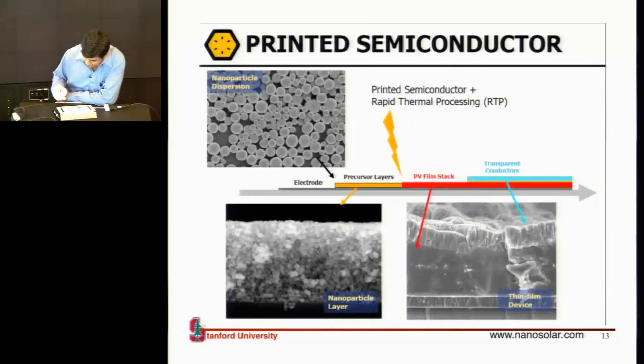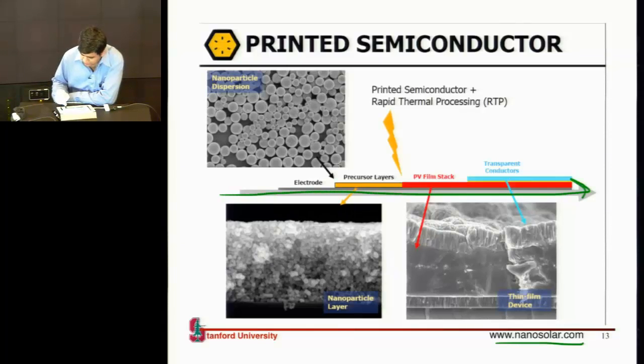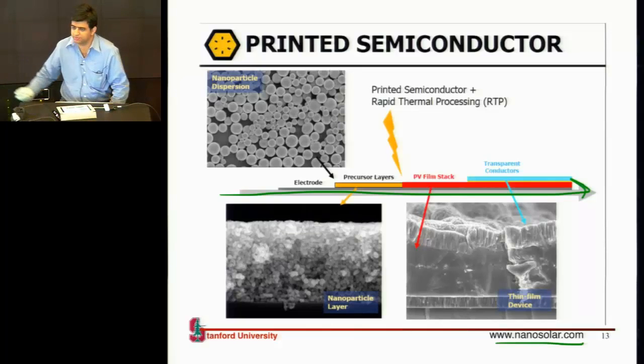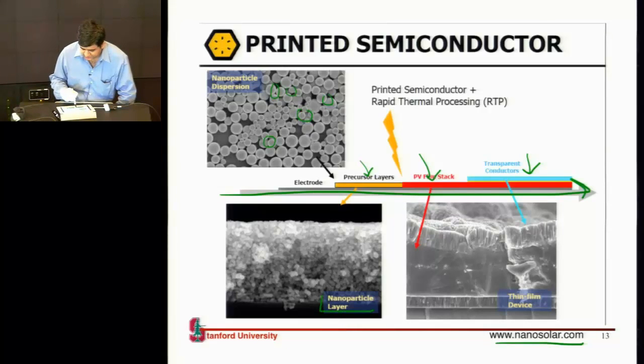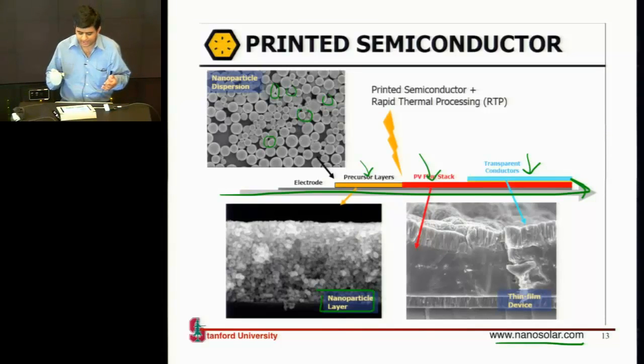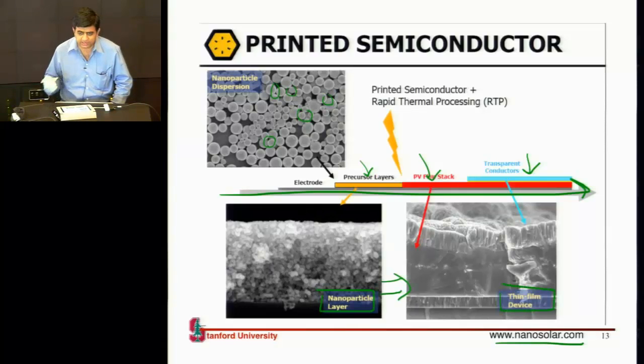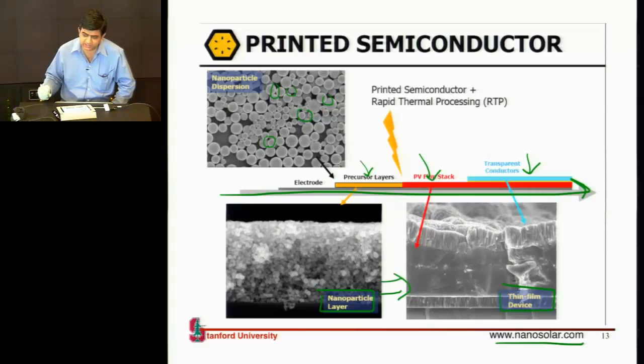This is from Nanosolar. They have an aluminum sheet which they are very quickly pulling through their different tools, and each tool deposits one layer of material. They deposit their CIGS material in the form of an ink. When first deposited it looks like nanoparticles, which is no good for a solar cell because there will be a lot of recombination. But afterwards they anneal it, and it turns out to be of decent quality. However, controlling the quality of this material is very difficult because this is a non-vacuum process — there will be other things incorporated, and the purity of the ink is debatable.